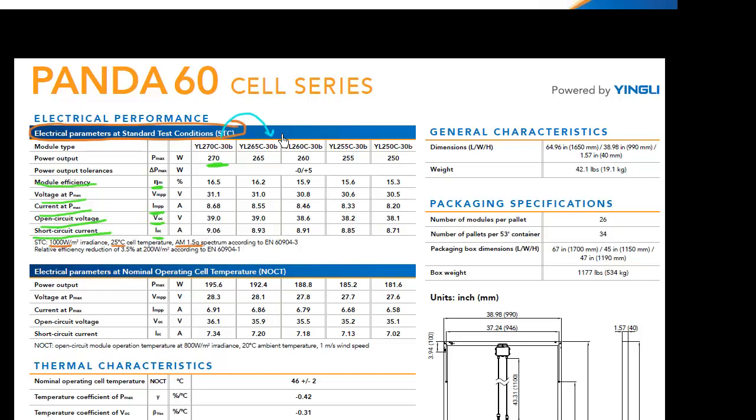Another thing to note is that there are these different columns over here. And they have very similarly lettered names. But you see over here that the efficiencies of these are different. And they are varying from all the way from 16.5 to 15.3. So what I've been done over here is that they all use the same cell. But the highest efficiency cells have been binned over into this module, which has the highest efficiency of 16.5. And all the bad cells or all the black sheep in the manufacturing line, they have been binned over into this particular module, which has the efficiencies of 15.3. But from a manufacturing process or from a cell perspective, they came out all from the same manufacturing line.